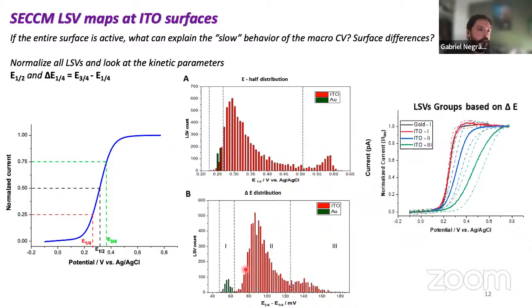as I mentioned, I think that's even more informative. We can see that on gold, we expect this to be near the 59 millivolts here, and that's dead on the distribution of gold if we do the experiment in gold. But if you look at the ITO, there's a very broad distribution, and it's not a monotonic one. We have at least 2 separate groups here. So we have an average population here, which is a little bit slow, and it goes towards the second group here, which is quite slow, right?